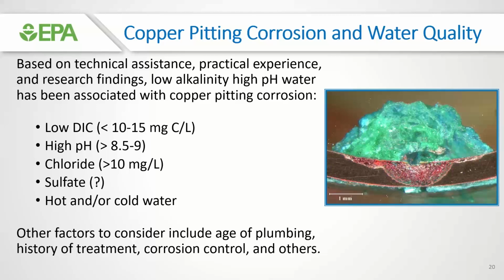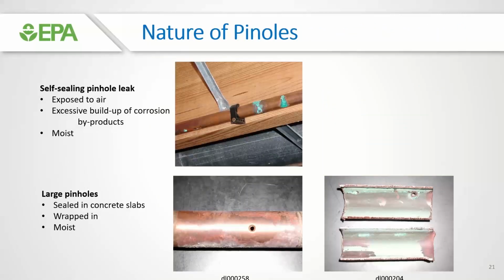And again, it can stray outside of those bounds a little bit, and sometimes it does, but those are the issues. And that's the water that I always say, boy, if you're changing your water source or changing your treatment, look out for that water. Be careful because, by the way, this is a great water for keeping copper levels low, but pitting corrosion, you better just be aware that it could raise some issues. Other factors to consider, including age of plumbing, history of treatment, and other things like that, we need to think about as well.